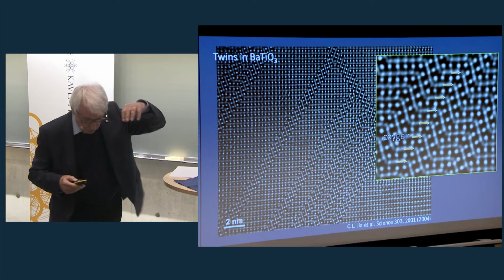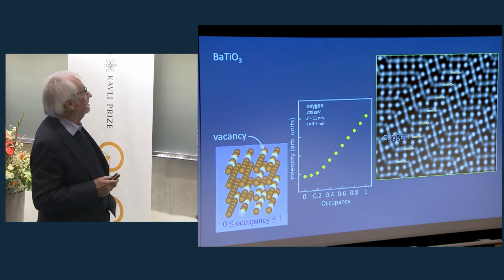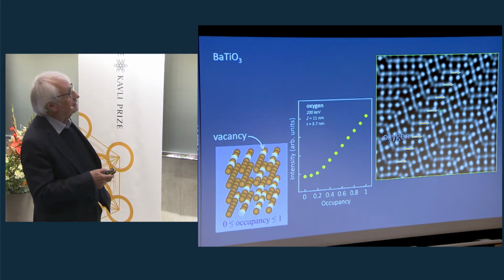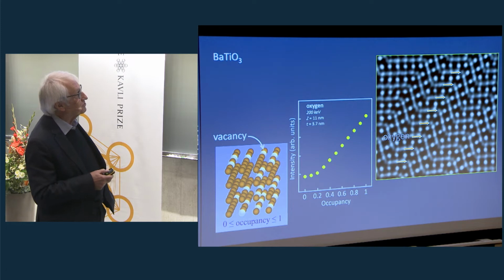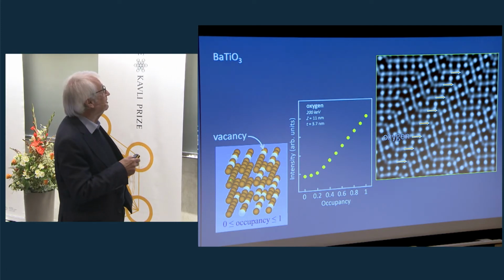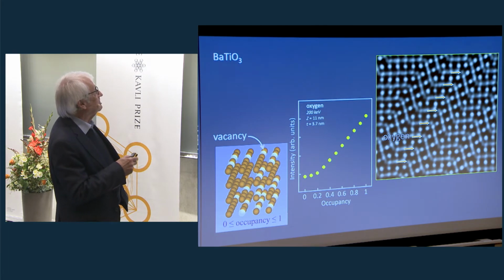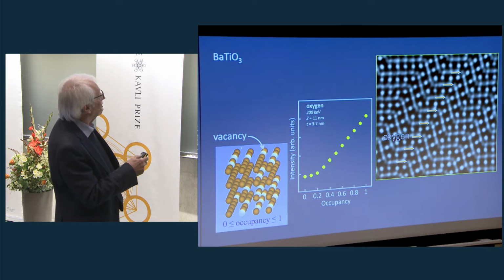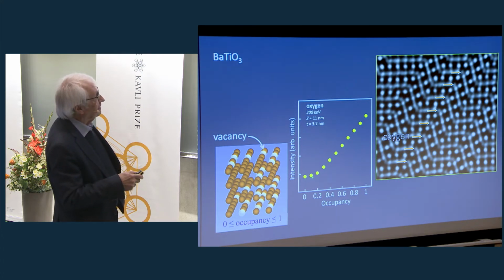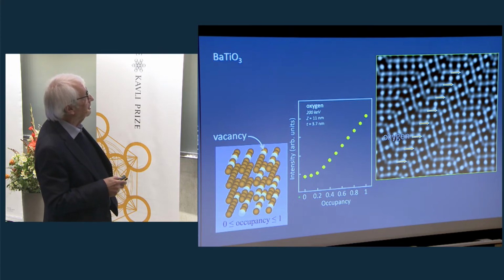So now I have just said that we look along the atomic rows, and we now calculated the expected intensity of the oxygen atoms as a function of occupation of these atomic rows. So each of these white spots here is a missing oxygen atom. So for all different concentrations of missing atoms, or the different numbers of occupied sites, we calculated the intensity. That means we have here plotted the occupation. 1 means full occupation, 0, no oxygen there at all, and here we have the intensity.